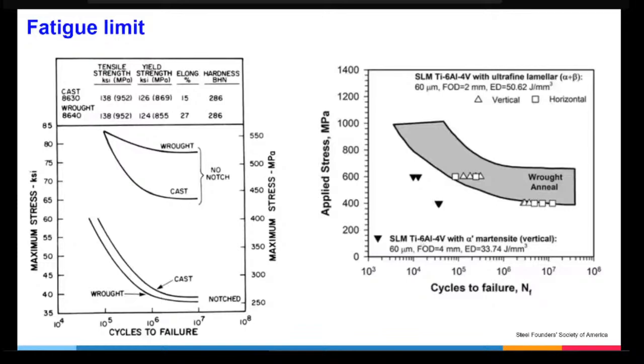This is quite natural because the additively manufactured component will have a higher amount of residual stresses in it and a higher amount of disorderness. So you cannot have the same properties in all the directions. So anisotropy in nature, basically. Different properties in different directions, higher amount of stress, and very importantly, the structure is not equiaxed. It is oriented in one direction with respect to build direction. All these three reasons contribute to the lesser strength under static and also under dynamic conditions, like fatigue. So whatever component we process by additive manufacturing needs to be tested for fatigue.